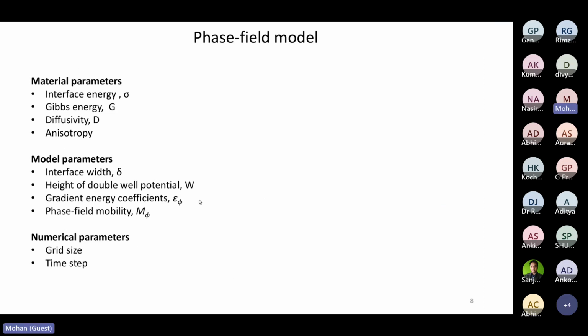So overall, I try to summarize the parameters which are mainly present in our models. There can be others. And while I am doing the demonstration, I'll try to explain how to get these appropriate properties, where to get them, and what range of values has to be chosen, so that you will get optimum results within reasonable time, and you need not spend much time on optimizing or deciding the parameters for the simulations. Basically, we have the material parameters: the interface energy, Gibbs energy, diffusivity, and the anisotropy, which decides the interface property. The model parameters are the height of the double well potential, interface width, the gradient energy coefficients, and the phase field mobility. And the numerical parameters are the grid size and time step.